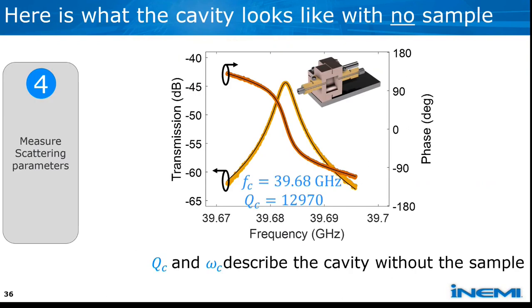So what does that mean? What does it mean to measure the S parameters of a cavity? Well, we're just going to measure the transmission through the cavity as a function of frequency. So here what I'm plotting is the transmission through the cavity as a function of frequency. That's the yellow curve right there with the black line through it. And on the right-hand axis, I'm plotting the phase through the cavity.